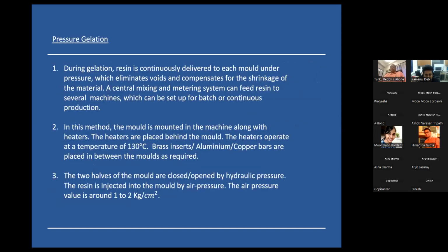So now pressure gelation is slightly different from gravity casting. Pressure gelation is used when you require batch production or continuous production. During pressure gelation, the resin is continuously delivered to every mold under pressure, and this helps in eliminating the voids. As I mentioned earlier, voids can decrease the performance of the component. In this method, the mold is mounted in the machine along with heaters. The heaters are placed behind the mold and they operate at a temperature of 130 degrees Celsius.